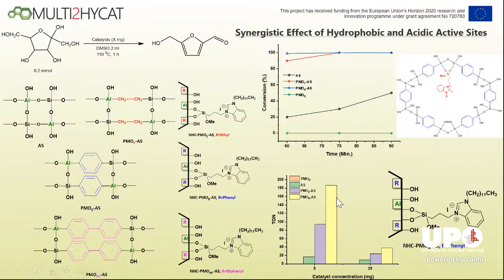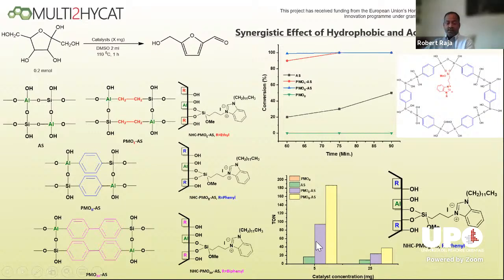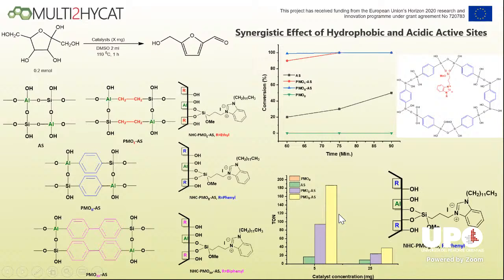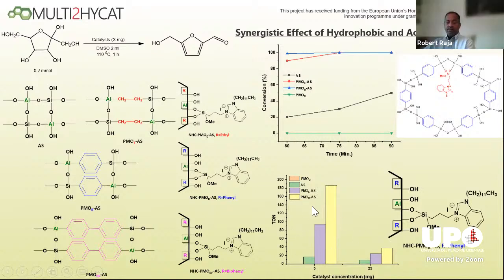We can then start to rationalize the degree of this hydrophobicity by looking at how the turnover numbers compare as a function of their catalytic potential. So if we look at the pure aluminosilicate analogs, they're quite low. But as you increase your degree of hydrophobicity in concert with the acidity, we now see this significant enhancement in catalytic turnover. So the conclusion really from here is, as part of this project, we can use our descriptors quite cleverly within these porous structures to bring into concert the synergistic effects of the hydrophobicity and the degree of acidity.